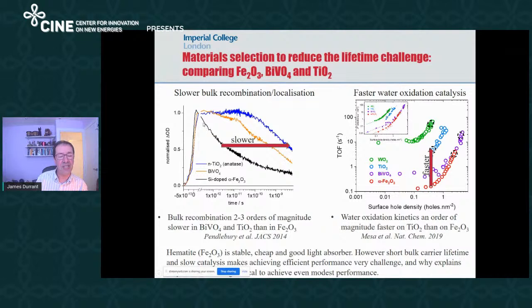So hematite has the fastest bulk decay times and the slowest water oxidation compared to the other materials. And that's essentially why hematite in principle is a fantastic material. It's very cheap, it's very stable, and it absorbs lots of sunlight compared to bismuth vanadate or titania. However, the kinetic challenge for hematite is far worse than either bismuth vanadate or titania, because you have to gain more lifetime to drive function. And that is essentially why, whilst hematite has all these good properties, the kinetics mean that ultimately it is not such an easy material to make into an efficient photoanode for water splitting.